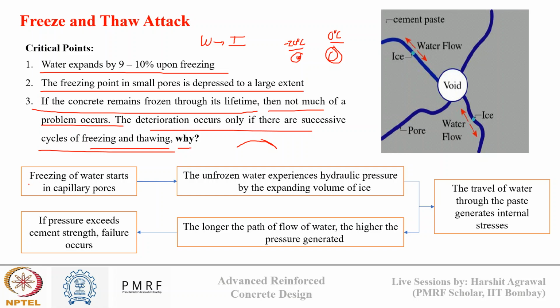So what happens, freezing of water starts in capillary pores. We have seen larger pores freeze earlier than smaller pores. So the water in capillary pores will freeze. Now due to this, ice formation will start. And as ice formation starts, the unfrozen water will experience hydraulic pressure due to the formation of voluminous, expansive ice.